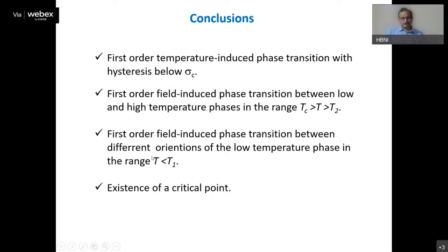So here the initial phase does not come, though both the transformed phases of different order parameter are stable phases. And another interesting point in this case, there is an existence of a critical point. So these are the conclusions we can draw for discontinuous phase transition under external field.